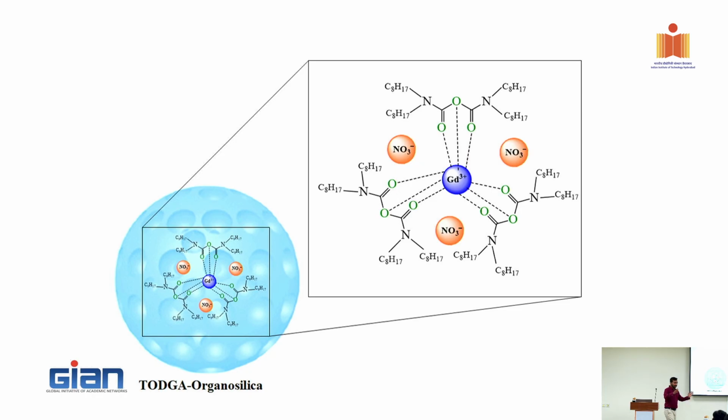So if I look overall at the coordination chemistry, or the complexing nature of gadolinium, that's how it chelates. It has 3 TODGA complexes, 1, 2, 3. In a nitrate media, it captures only gadolinium by this specific oxygen-oxygen bond. This fits exactly into the ionic radius of the gadolinium. That's why ionic radius plays a crucial role in selectively capturing gadolinium from the nitrate media in the urine solutions. So this is a simple case study of how we deal with the concentration.